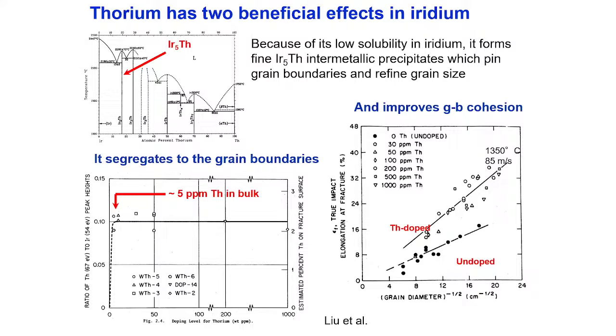But the thorium also segregates to the grain boundaries. If you plot the amount of thorium on the grain boundaries as a function of the thorium in the bulk, it rapidly saturates around 5 ppm thorium in the bulk. Beyond that, you don't get any more thorium on the grain boundaries, and that's because the solubility limit is so low. So anything above 5 ppm ends up as a precipitate, and below 5 ppm, it saturates all the grain boundaries.